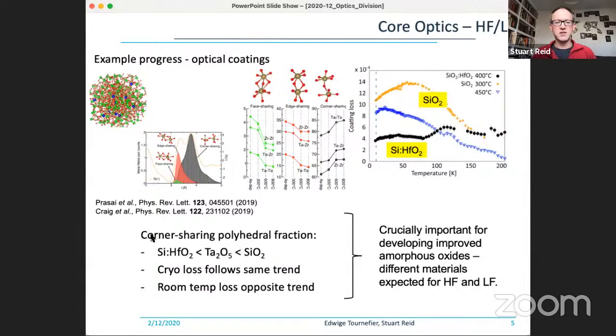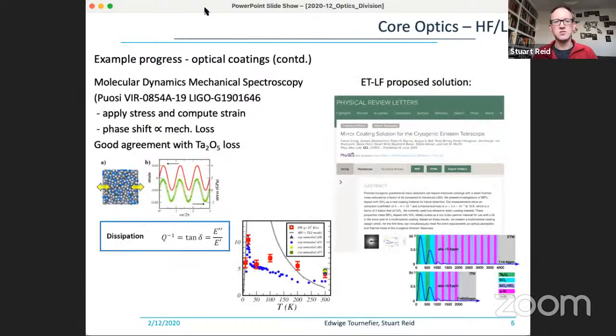And so there's this effect where we look at the corner-sharing polyhedral structure within the materials. If we link the materials studied in these two papers in order, we've got silica hafnia, then tantala, then silica. And the cryogenic loss follows this. So silica hafnia has the lowest mechanical loss. We can see that here. And silica is the highest. But when we look at the room temperature mechanical losses, we get the exact opposite trend. And so this is very informative for our studies within the Einstein telescope, because this suggests that if we were using amorphous oxide materials, we're very likely going to be choosing different materials for the high frequency and low frequency components because of these opposing effects with the mechanical loss.